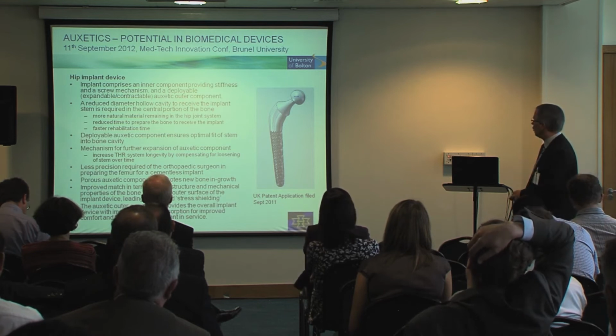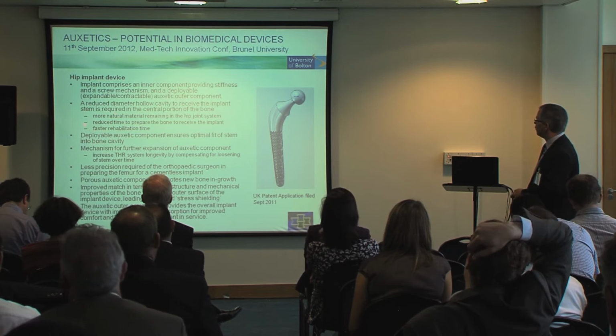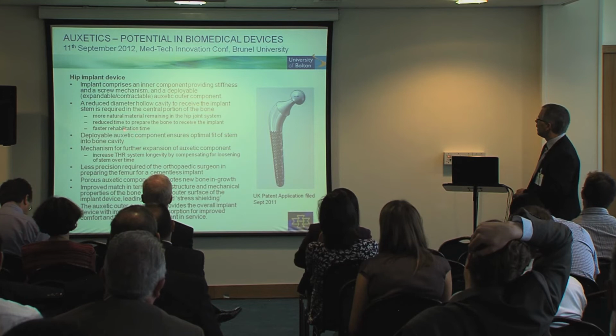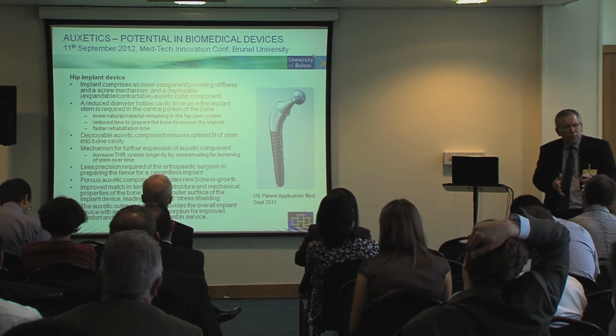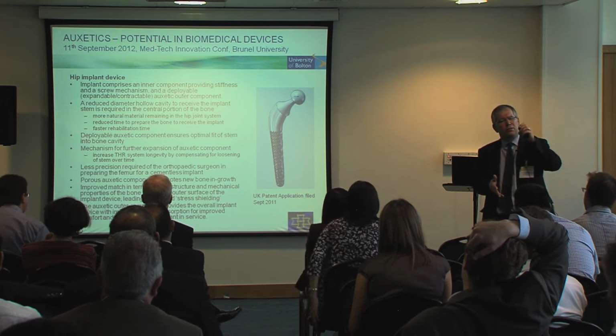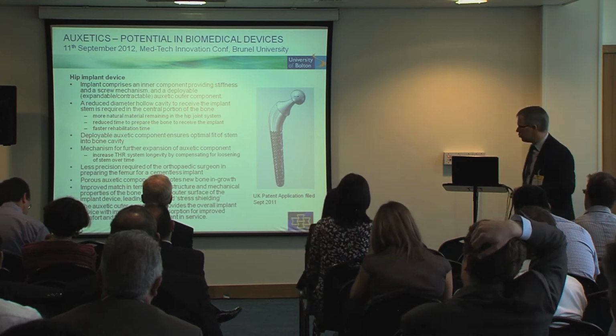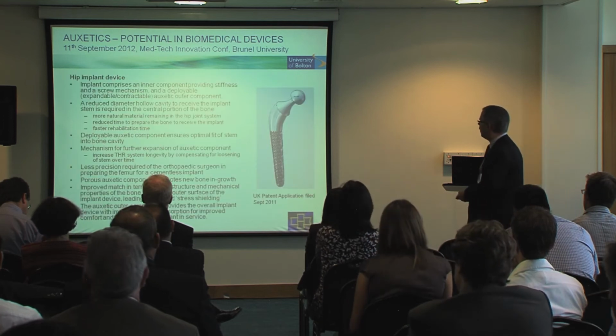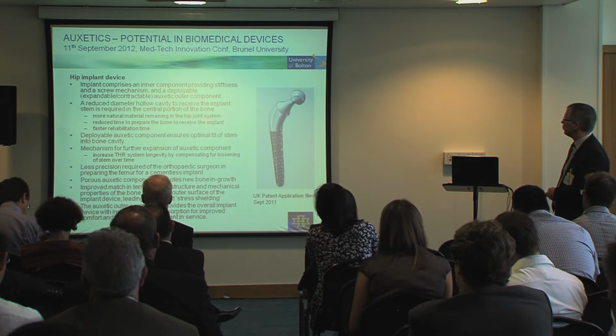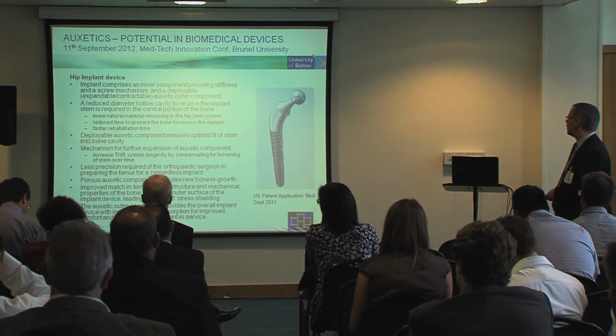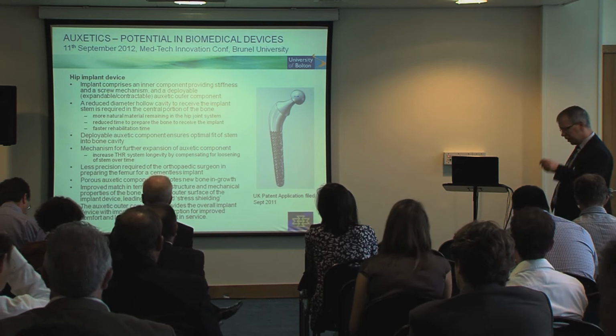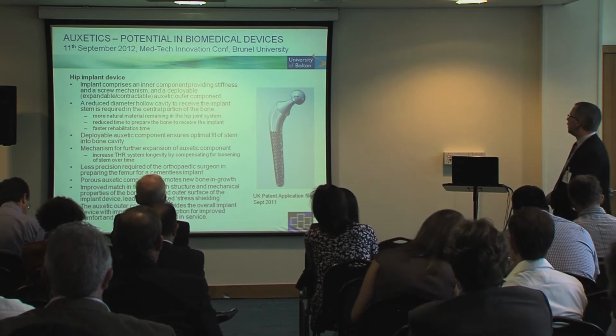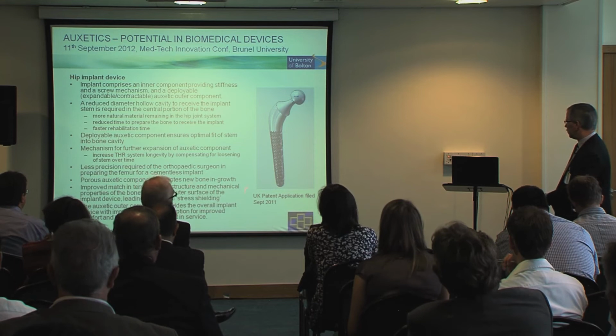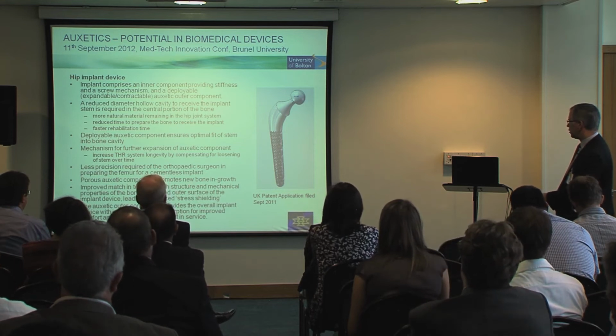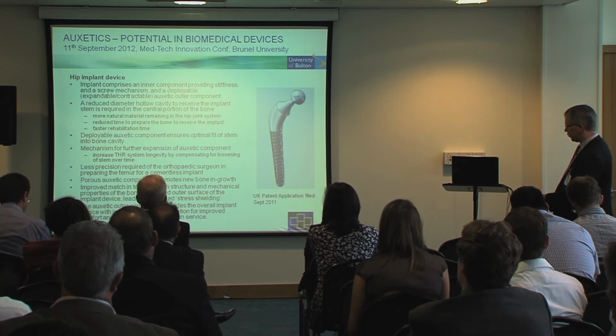Okay. So we think we can come up with a device where we've got this deployability function. If it's deployable and starts in a lower volume state, therefore we require to take less bone out to actually receive the implant, which should be a benefit, but more natural material existing, reduced time to prepare the bone to receive the implant, and faster rehabilitation time. We can optimally fit the stem by applying the right amount of deployability. And that's pretty much it. The porous part gives us new bone ingrowth. We've mentioned the reduced stress shielding effect, and the energy absorption properties, which should also be a benefit.